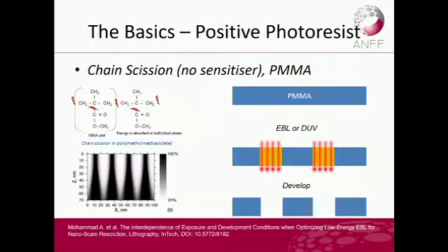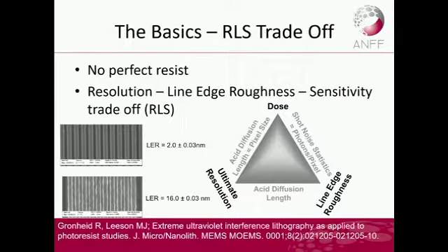It will turn this big polymer into smaller fragments and make them soluble. And you can see this is a simulation diagram of the depth of the film, and you could also generate something similar to this because the intensity is higher on top, and then the intensity will gradually reduce. This is in the case of the deep UV process. So once you develop, you're left behind with the area that has not been sectioned. The beauty with the chain scission process is that the sidewall and the resolution are very, very high because you don't have the diffusion problem. Also, you don't even need a post-exposure bake process.